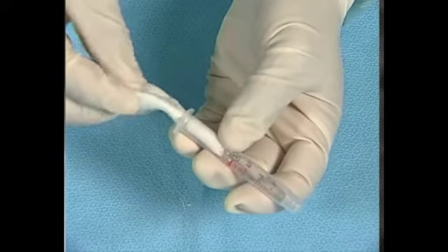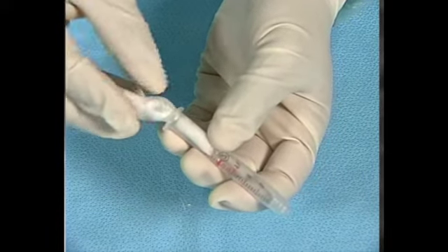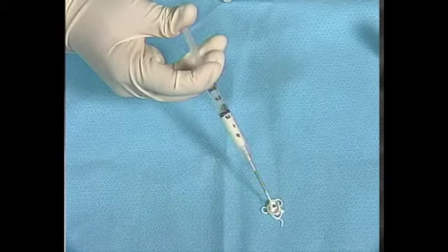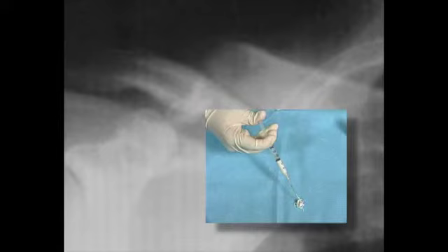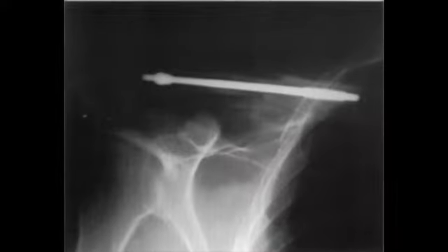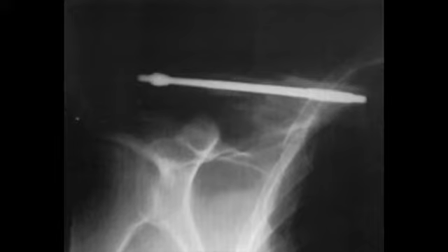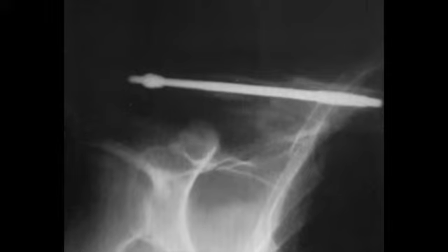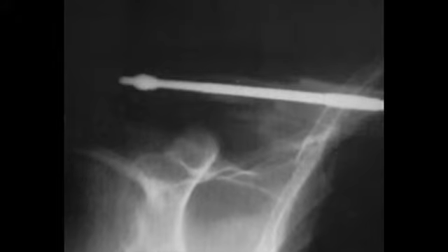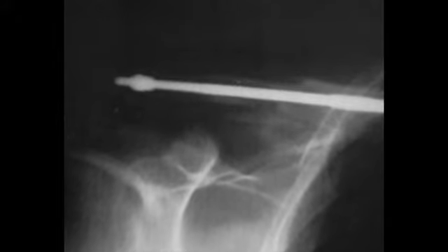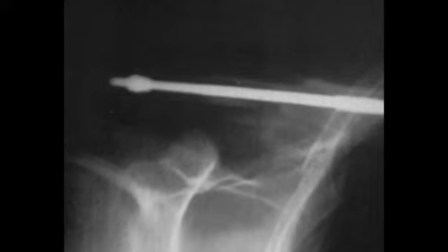Before the pin was inserted, alpha BSM was transferred to a syringe fitted with an angiocath catheter, which was inserted into the lateral fragment. ABSM was injected, acting as osteoconductive filler within the medullary canal, filling any possible non-visible bony voids. The clavicle pin was inserted in a retrograde fashion and allowed to pierce the skin laterally. The alpha BSM injection technique was repeated with the medial fracture fragment, and the clavicle pin was passed into the intramedullary canal. The clavicle pin reduced the fracture and applied compression across the fracture.